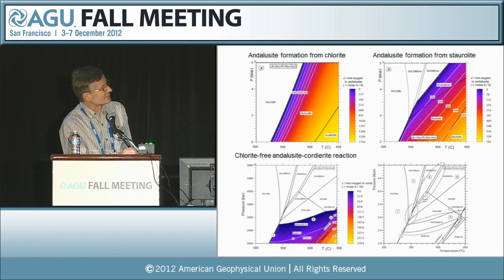So you can see that there's a color variation from low amount of reaction affinity to high. And I've put some contours on here to accent the differences between the three reactions. So this one is the chlorite to andalusite reaction. It's a high entropy reaction. This is the chlorite-free staurolite to andalusite reaction. And this one down here is the andalusite to cordierite reaction.